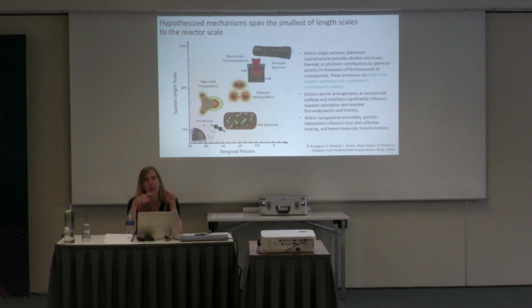The bulk plasmon resonance is that metal to dielectric transition resonance, and that changes between about 6 and 8 eV. But the surface plasmon resonance, or that gap mode resonance, doesn't change very substantially.